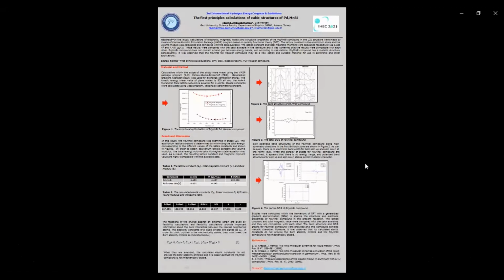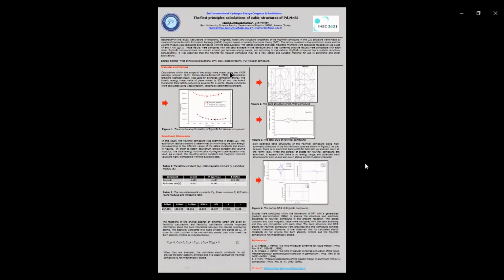In this study, the equilibrium lattice constant is determined by minimizing the total energy corresponding to different values of the volume, shown in Figure 1. The value corresponding to the minimum energy from this chart gives us the numerical value of the lattice constant. Table 1 shows the lattice constant, total magnetic moment, and bulk modulus for this compound.